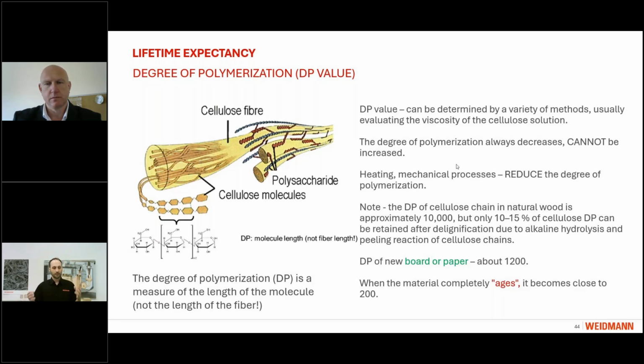And so we can state that as soon as this tree is cut down, this degree of polymerization will not increase anymore. It can only be decreased by processes. Now, when we talk about the DP of new board or paper, we are roughly in the ballpark of 1,200. There are some that are higher, some that are lower, but this is roughly the ballpark you can place it in. Now, when we say the material is at its end of life, then the degree of polymerization is rather 200, and it is very brittle.